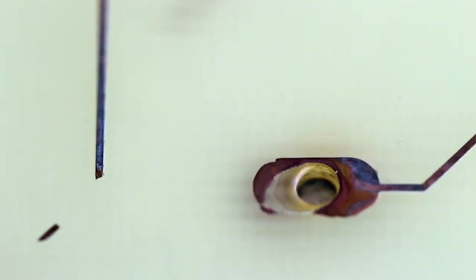If the minimum pad size is not adhered to then there's a possibility that the drill holes will not be protected adequately and the through hole copper plating can be washed out in the etching process.